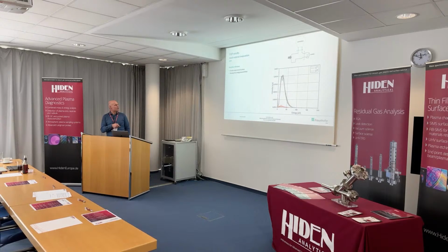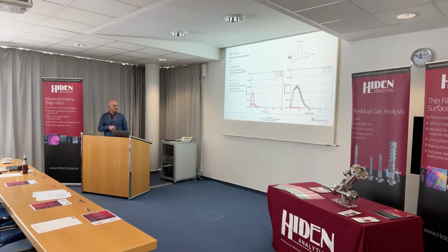And the average ion energy is a value we also know from the literature, and it is around 30 eV for the single charged ions. Now this scale is changed to voltage, and if you want to get to electron volts, you have to multiply by the ion charge state. This is two times ionized, so it moves to the right side, of course. And for boron, it's the same. If we compare boron and carbon, we see it's very similar, and it's also in the same range for the two times charged and the single charged ions. And this is something we also see if we use a plasma filter. We have the same relation between carbon and boron in the film, whether we do filtering or no filtering, it's always the same, because they are in a similar energy range, and so they are filtered the same.